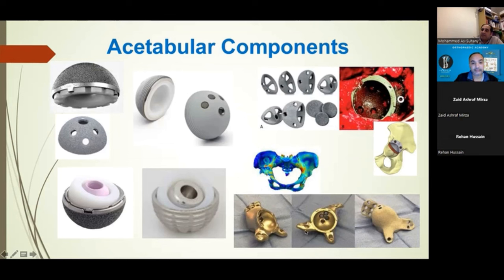So the idea with this kind of implant is that you've got the socket, and then you've got this tri-flange, three anchor points that you can then secure into whatever bone is left in that hemipelvis, in the ilium, pubis, and ischium. Then you can cement into this. It's almost like you're creating your socket, your native acetabulum, and then you can put your implant into that. So this is a triflange or custom made: you get a CT scan, work out the defect, and then you can reconstruct it. This is far down the reconstruction ladder, but these are just flavors of what's out there for the acetabular components.